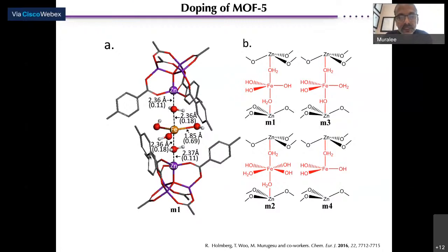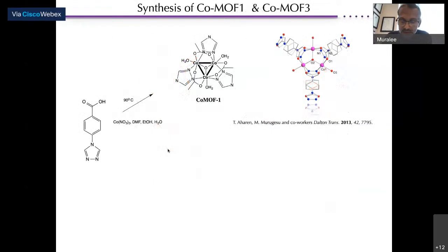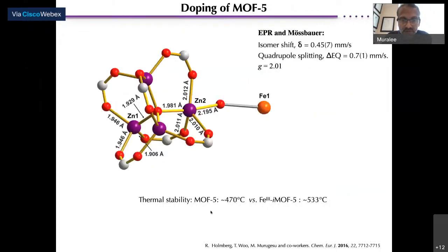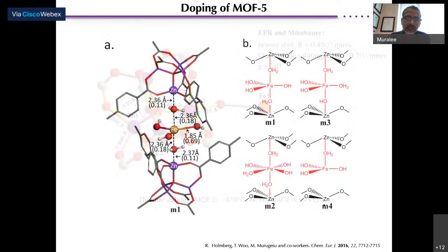So we do believe for sure that it is the iron 3+ ion which is present, and it's also linking the tetrahedral unit of these two interpenetrated frameworks to form this stable MOF5. Just to mention, I went quickly, the thermal stability of MOF5 is around 470 degrees Celsius. Now, due to this linking of this interpenetrated system, you're going much higher in thermal stability for this system.